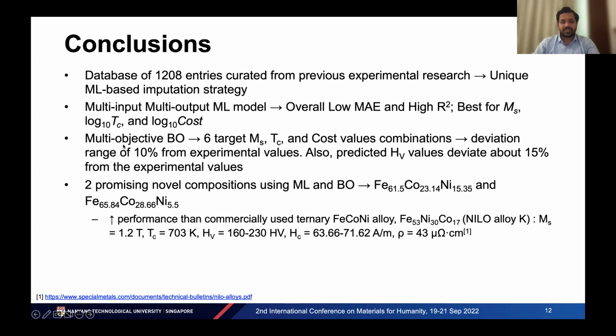Further, a multi-objective Bayesian optimization was used, wherein six target combinations of MS, TC, and cost were used. And the overall deviation for these three properties was in the range of 10% from the experimental values. Also, the prediction of the HV values deviated only 15% from the experimental values.